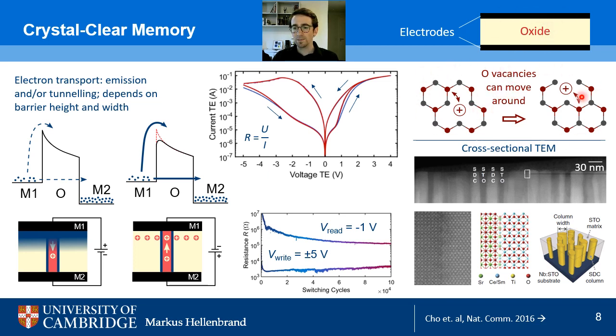So if we have a crystal with a certain amount of oxygen vacancies, then these oxygen vacancies can actually move around inside the crystal. This is because the bonds between atoms in this lattice have a certain strength. So by providing energy to the atomic lattice, we can break some of these bonds, and atoms which previously were fixed can move to a different place, such as illustrated here, so moving from up here to down there. Consequently, the oxygen vacancy, which previously was down here, effectively moves up here. So by moving atoms around, in effect, we can also move oxygen vacancies around. And the energy required for this can just be supplied by applying a voltage to our simple structure.